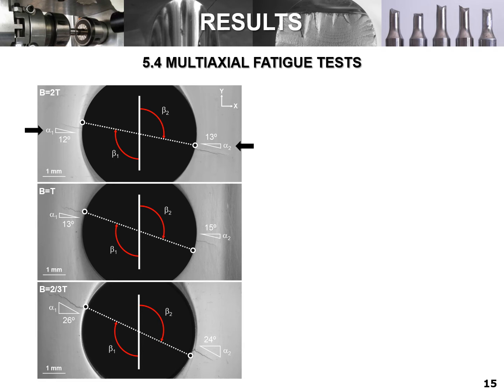Regarding the crack angles at the early stage of growth, represented in the figures by alpha, the experimental measurements show that they decrease with increasing values of BT ratio. Not surprisingly, higher BT ratios reduce the predominance of shear stresses, and therefore the crack fronts tend to be closer to mode 1.